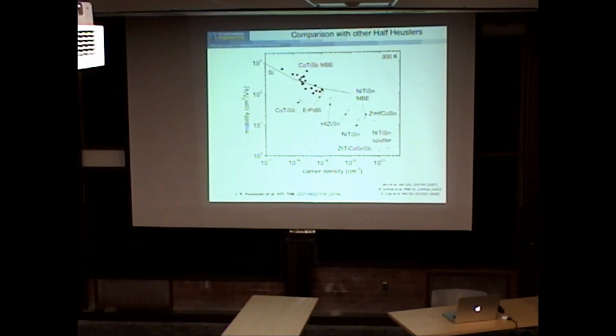Okay, so now what about the properties? Here I've plotted the carrier densities we've measured in our films and compared them with silicon of the same carrier density, and here's cobalt titanium antimony. The lowest we got down to is maybe 5 times 10 to the 17, and we get a room temperature mobility of about 500. So this is about the same as that of silicon. We think this is pretty exciting, because now we have a completely different material with somewhat similar properties to silicon. You can think of it as the same indirect type band gap semiconductor.